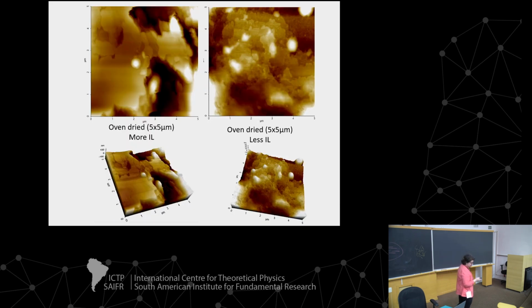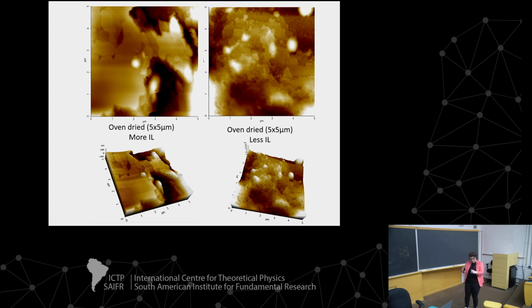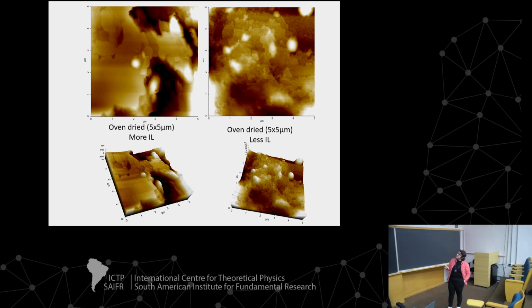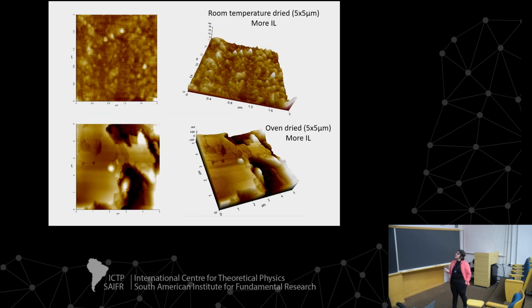We see this by atomic force microscopy. We can see a small piece here. We have different self-assembly. When the same material is dried in an oven with more ionic liquid, it is a continuous plaque. But when we have less ionic liquid, we have this particle assembly like shells and layers, different layers. This is a very interesting kind of arrangement and affects the sensor directly. Here we have the material again dried at room temperature. We can see the particles covered by the ionic liquid. And here is the same material dried in an oven. It's a completely different morphology and different properties.